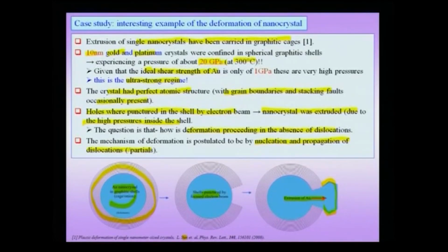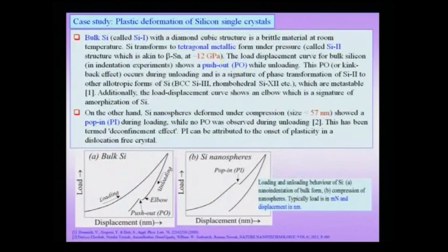a nano hole. So, this is a very nice kind of an experiment, and you can clearly see that the kind of pressures we are talking about, the kind of mechanisms we are talking about, the kind of experimental issues in actually observing some of the effects is very difficult, and we have to do secondary computations like molecular dynamics to actually come up with a mechanism like this partials or full dislocations moving through the crystal and leading to this extrusion.